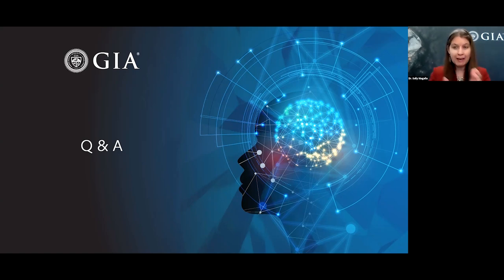HPHT grown rough have passed the 100 carat mark. That's for rough, not for faceted, but a couple of HPHT grown manufacturers have passed that 100 carat mark. I don't know when or if that's possible for CVD grown diamonds. A couple of the limiting factors for CVD is with extended growth, you start to go from single crystal to, say, polycrystalline to non-diamond crystal growth.